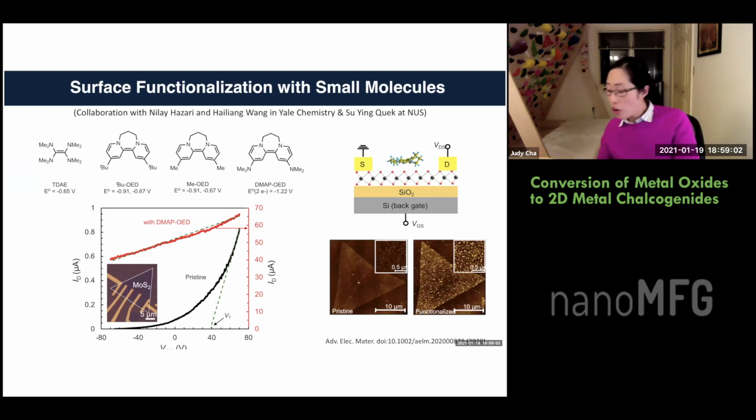Of all the characterization techniques that we tried, we believe AFM is the best to count the number of molecules. If you want to know how many electrons a molecule should donate, you measure the change in the carrier density. That's straightforward. You just make a device, and then you have to count how many molecules you have. Counting how many molecules you have is actually not that simple.